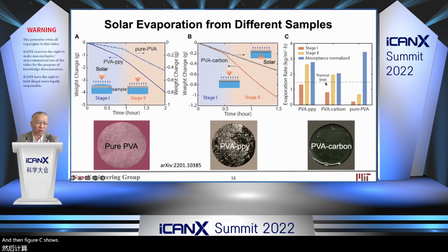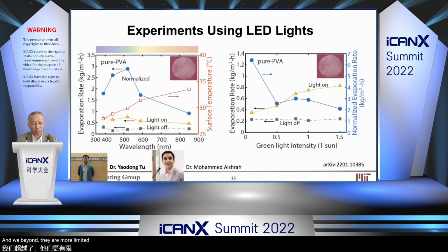And then figure C shows the evaporation rate. For pure hydrogel, after we normalize to absorptance, it actually is the highest evaporation rate, and way beyond the thermal limit. We also did an LED, and interestingly, even pure hydrogel without any absorber, the peak happens at the green light, 520. And lower intensity, on the right, actually gives us an even higher evaporation rate. That's the blue curve you can see. So those are what's happening on the evaporation rate.